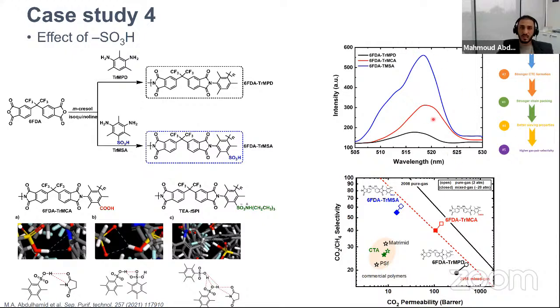So what does this mean? This means if I have higher fluorescence intensity, then I have stronger charge transfer complex formation. And then we have stronger chain packing, which results from the stronger interaction between the chains. And thus we have better sieving properties. And if we have better sieving properties, it means our polymer is going to favor some gases going through over others. And thus we achieve higher gas separation